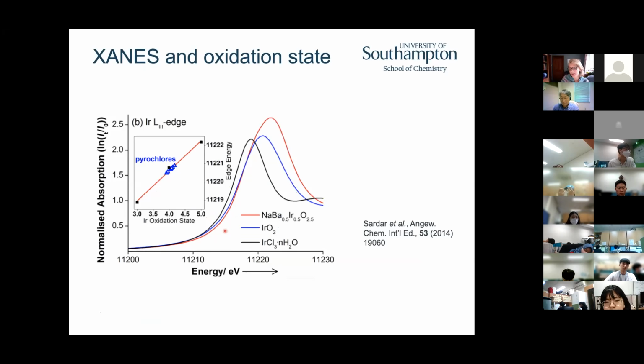I can do the same thing with iridium. Here we tend to use the peak position instead of the edge position. But again, I can have my 3 reference compounds with different oxidation states of the iridium, and that allows me to create a calibration plot.